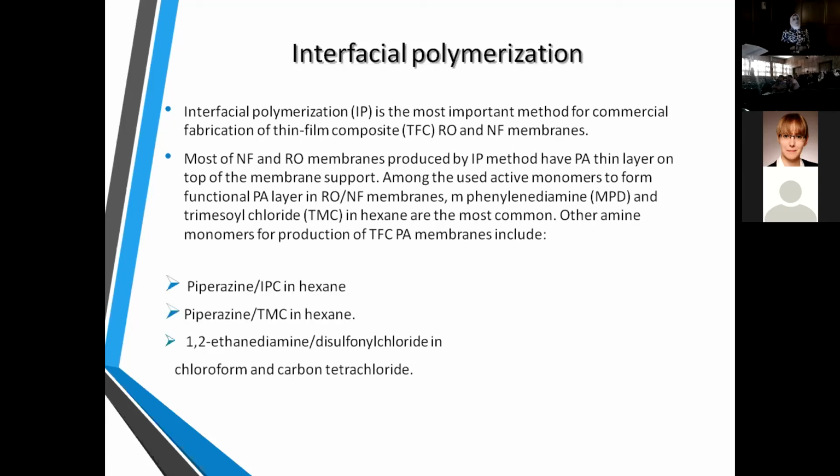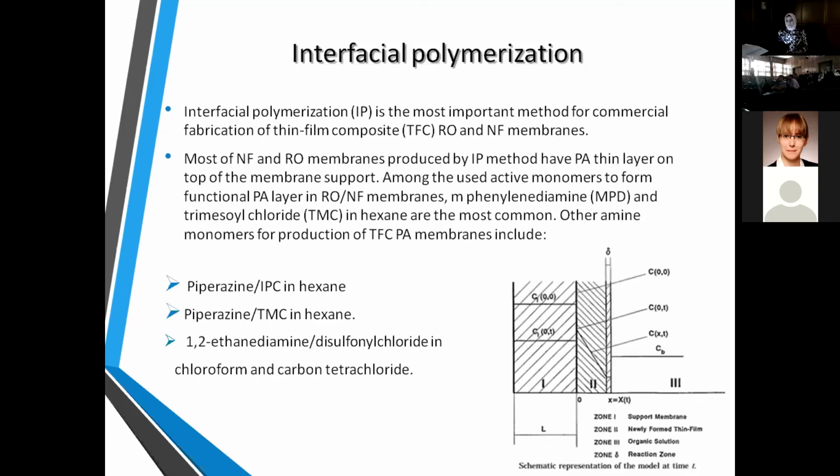We can also use piperazine with isophthaloyl chloride and hexane, piperazine with trimesoyl chloride and hexane, and 1,2-ethane diamine with disulfonyl chloride and chloroform, and carbon tetrachloride.